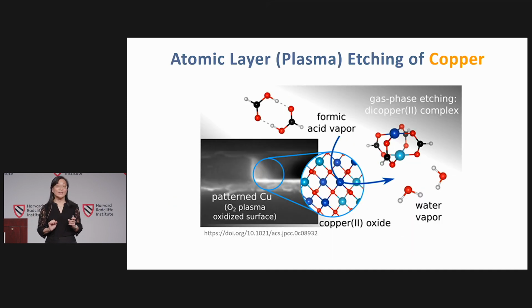Coming back to the point of the talk, atomic layer etching is a wonderful process, and my group has demonstrated that we can use this process to remove atomic layers of copper. We do so by using an oxygen plasma, and we use this particular process to modulate and control the directionality of the formation of copper oxide. Then we use an organic acid vapor to react with the surface and selectively remove the copper oxide from the surface, forming these complex and volatile compounds.